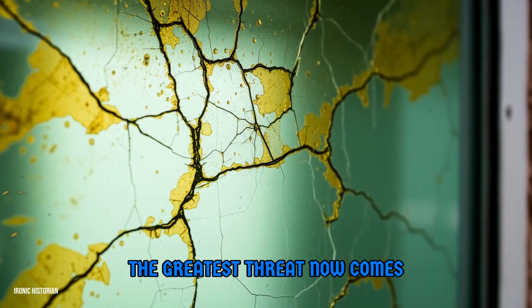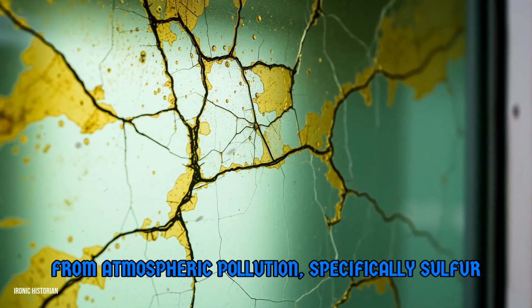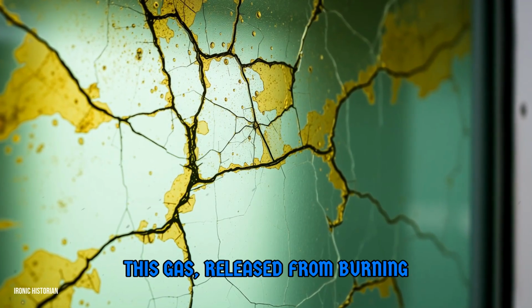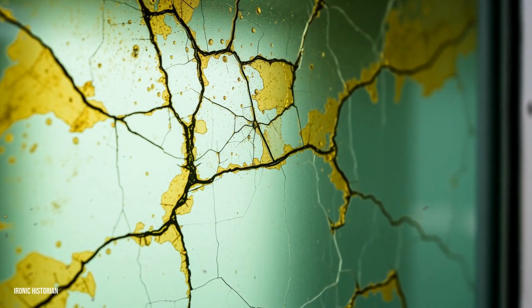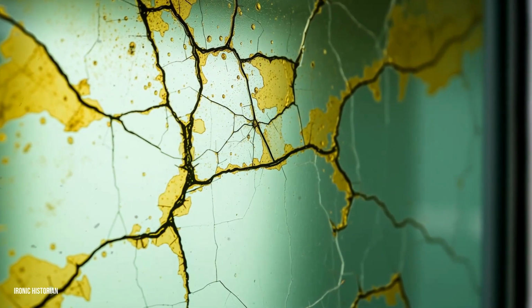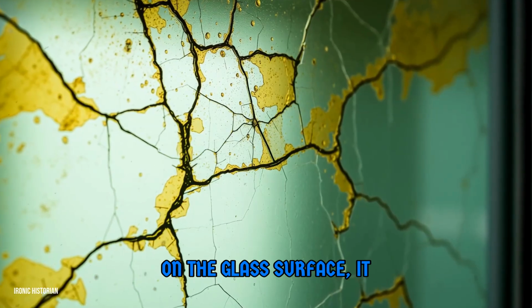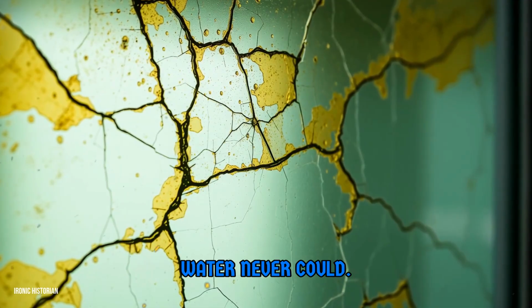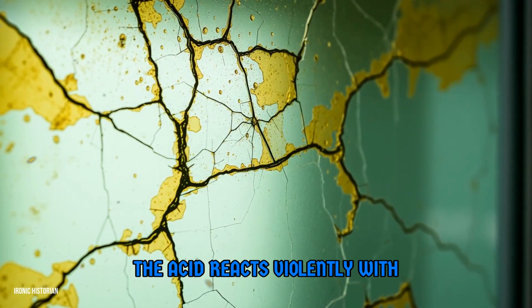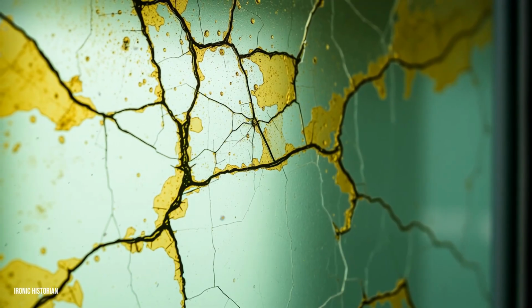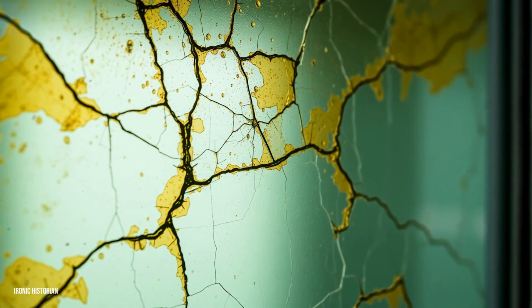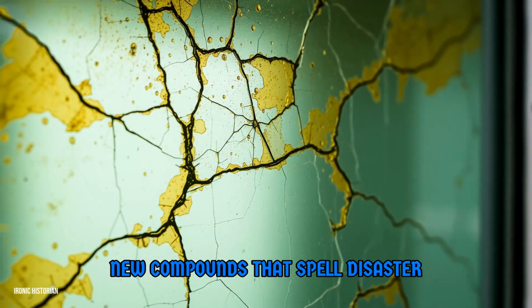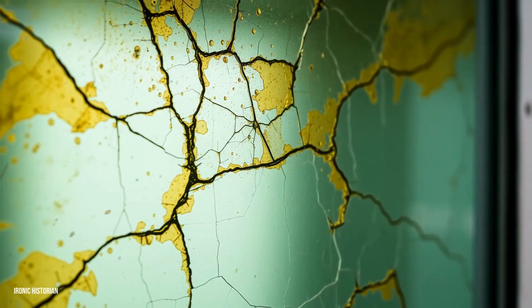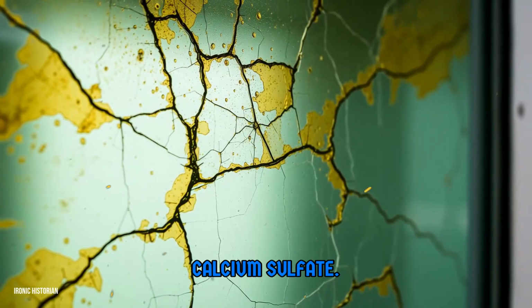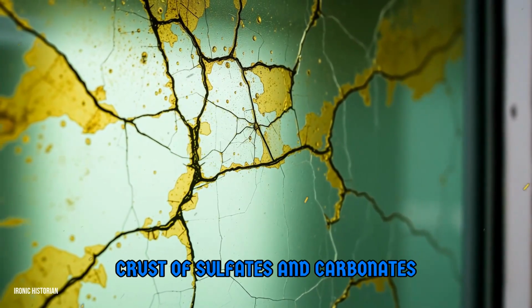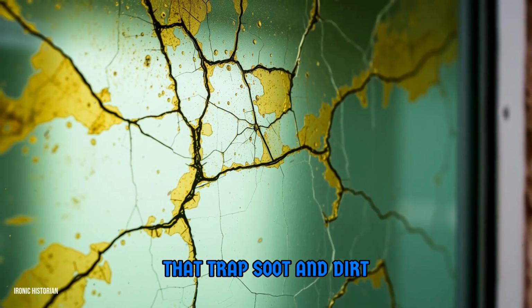The greatest threat now comes from atmospheric pollution, specifically sulfur dioxide. This gas, released from burning coal and other fossil fuels, dissolves in water to form sulfuric acid. When this acidic moisture settles on the glass surface, it attacks with a ferocity plain water never could. The acid reacts violently with the glass's protective gel layer and the calcium within the glass itself. This chemical reaction produces two new compounds that spell disaster for the window. The first is gypsum, or calcium sulfate. The second is a complex crust of sulfates and carbonates that traps soot and dirt from the air.